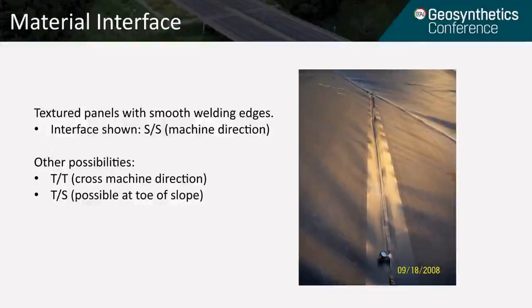The overlap is your interface area, the bottom of the top sheet and the top of the bottom sheet, what those two materials are. In this case, it's smooth and smooth, but it could be textured if you're on a cross machine, a butt seam, and textured and smooth might be possible at other areas as well. And each of those combinations of interfaces is going to change the welding parameters for that particular interface.